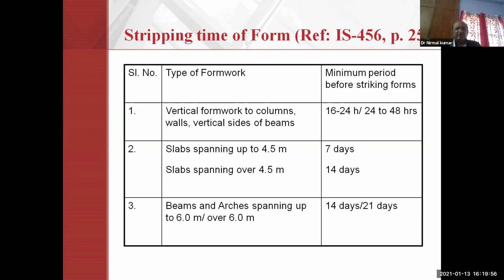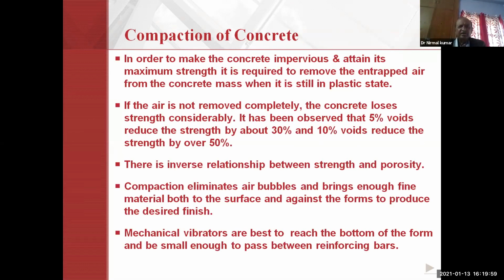Now, the important issue related to the compaction of the concrete: it should be placed and immediately compacted by means of mechanical vibrators. If voids are there, 5% voids reduce the strength by about 30%, and 10% voids reduce the strength by over 50%. There is an inverse relation between strength and porosity. Therefore, compaction eliminates air bubbles and brings enough fine material both to the surface and against the forms to produce the desired finish. Mechanical vibrators will be used.